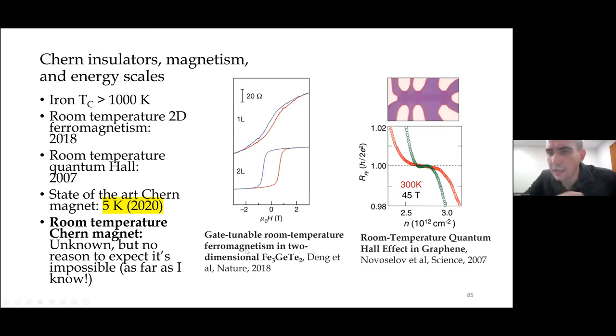And of course, as most people here probably know, there's no intrinsic energy scale to topology. It's just a property of a band. And indeed, room temperature chiral edge states have already been observed in graphene at high magnetic field in a quantum Hall state, right? So although it remains true that the highest Curie temperature Chern magnets are around 5 Kelvin, maybe 6 or 7 Kelvin generously, there's not really any reason to expect that very high temperature Chern insulators might not be realized in other systems, perhaps even outside of moiré superlattices. And in that limit, these phenomena should allow electronic control of magnetism in a pretty wide variety of systems.